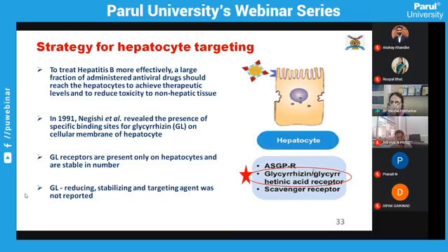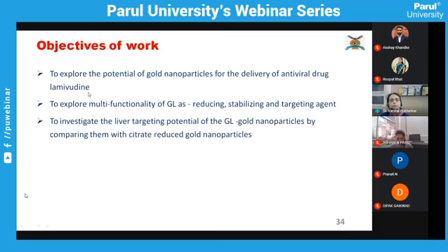When we looked at the literature, we found there was no report on the use of glycyrrhizin as a reducing, stabilizing and targeting agent using gold nanoparticles, so we thought it would be good to explore whether we can get efficient targeting using gold nanoparticles exploiting the glycyrrhizin receptor. The objective here was to explore the potential of gold nanoparticles for the delivery of the antiviral drug we selected, lamivudine, and to explore the multifunctionality of glycyrrhizin as a reducing, stabilizing and targeting agent. So it is a three-fold application using just one single agent.